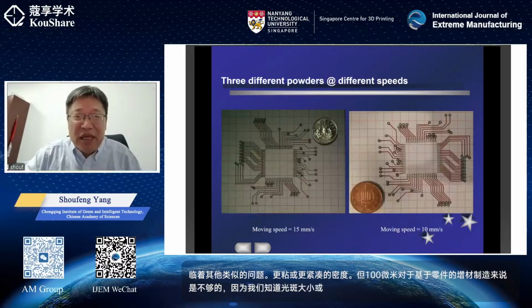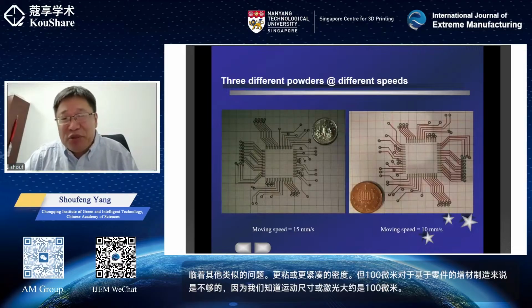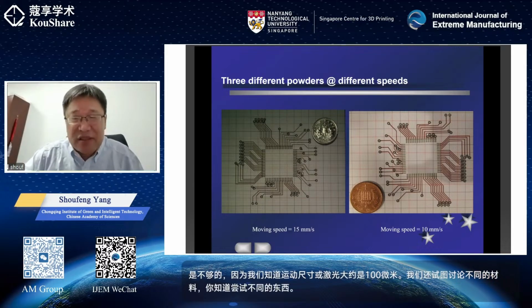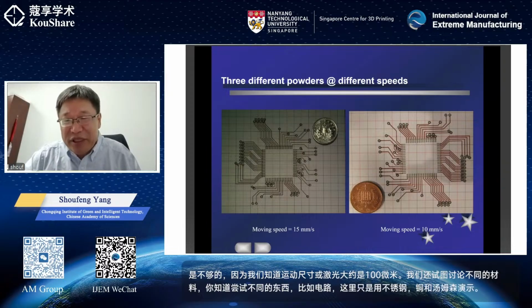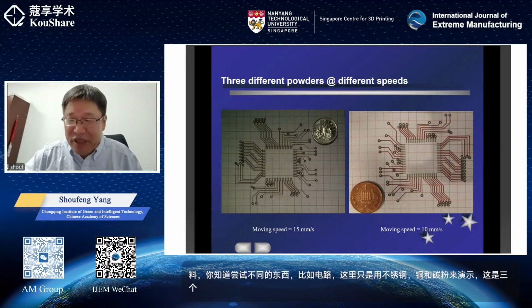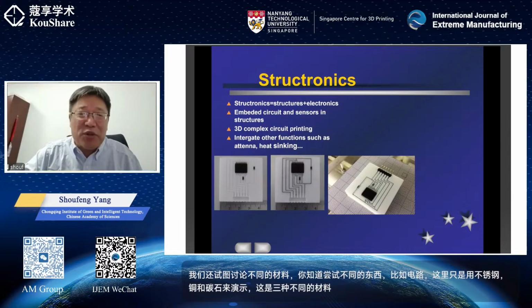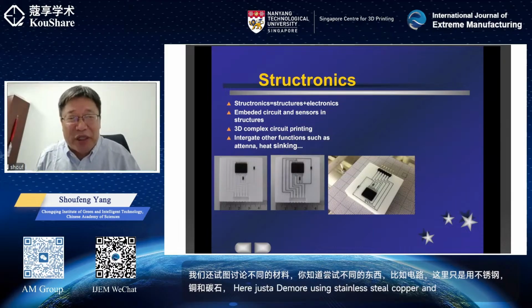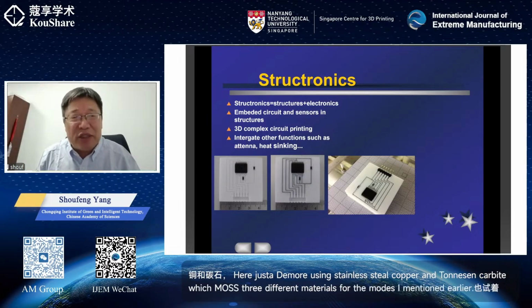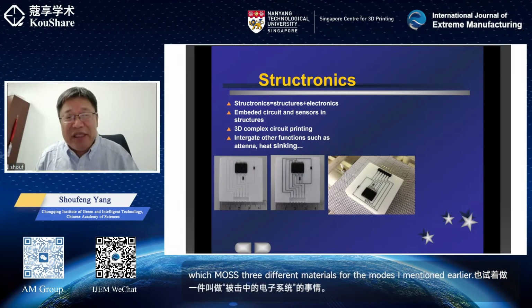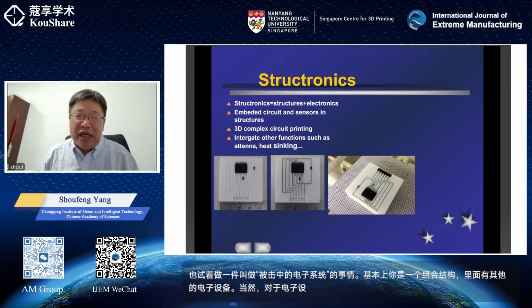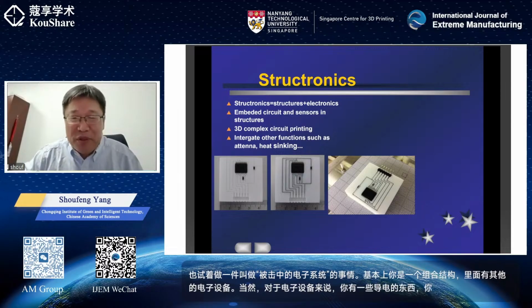So, we also try to dispense different materials, something like a circuit. Here is just a demo, using stainless steel, copper, and tungsten carbide, which are 3 different materials for the modes I mentioned earlier. And we also try to do something called structronics. Basically, you combine a structure with electronics inside. Sure, for electronics, you have to use some conductive materials, and you can't print the chips. You have to insert them.